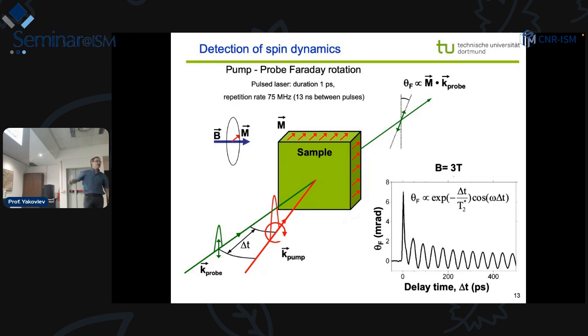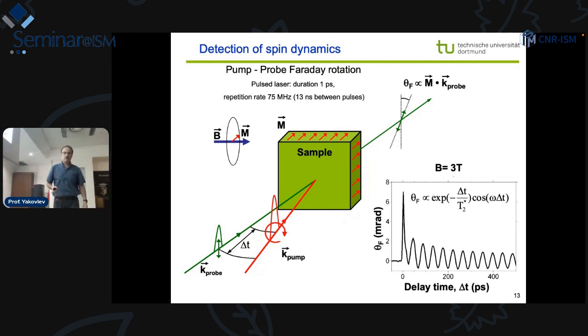From the period of this precession, we can directly measure the Zeeman splitting, or the Landé g-factors, and the decay of this signal is the so-called spin dephasing time. There is spin relaxation time when we talk about a single spin, and spin dephasing time is when we talk about the decrease of polarization of a spin ensemble, because spins may precess at different frequencies.